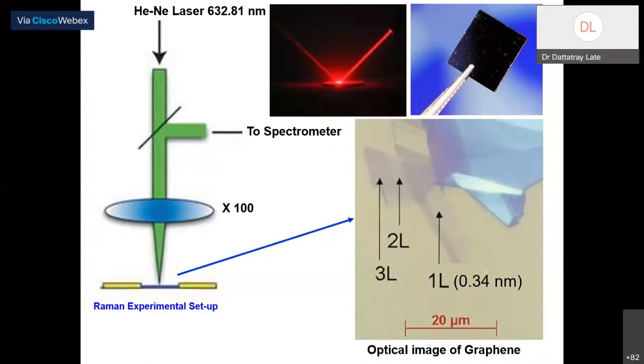Of course, I can also do a very important study by Raman spectroscopy. You can see here another image taken under an optical microscope. One layer of graphene is almost transparent in color. The thickness of this layer is almost 0.34 nanometer theoretically. The moment you move from one layer to two layers, you can see the contrast has improved slightly, and then three layers. Here you can see very light and dark colors. These are multi-layer, maybe more than 10-15 layers of graphene. So with just a simple optical microscope, you can identify whether a graphene sample is one layer, two layer, three layer, or multi-layer. So this is an advantage.